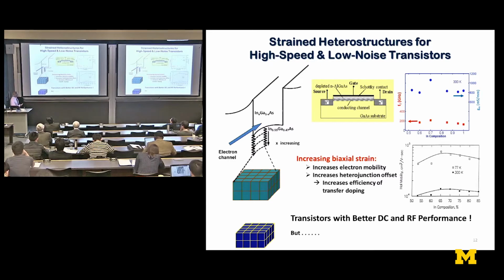And what you have here is a modulation-doped high bandgap, low bandgap heterostructure. And the electrons then transfer to the low bandgap material, and that forms the high mobility channel. And actually, the inventor of this device, Mimura-san, he got the Kyoto Prize this year. So we started with indium phosphide-based heterostructures, and in the channel we started adding more and more indium to lower the band gap, increase the mobility, and also that increased the band offset and therefore the transfer doping efficiency.